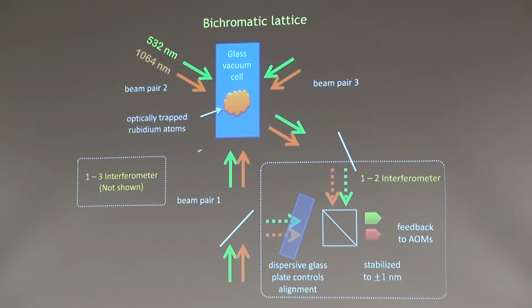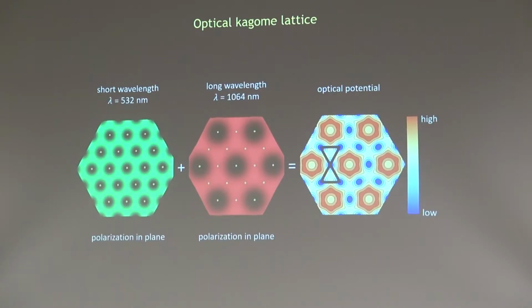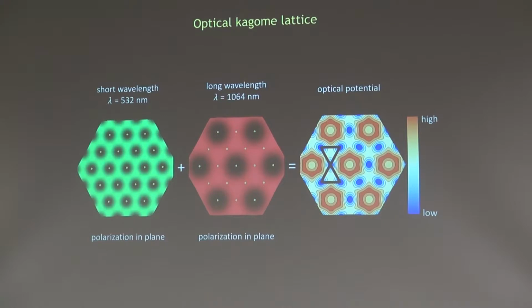And as I'll show you in a second, we're interested in forming an optical lattice or an interference pattern from the intersection of all these green beams. And on top of that, another optical lattice from the intersection of these infrared beams. But we're very interested in the relative position of these 2 optical lattices. And in order to stabilize that relative position against drift in mirrors and air currents and such on the table, we use some active stabilization at an interferometer, which now is tuned pretty well to where the relative position of the 2 lattices is stable to within about a nanometer. So that means we can create this kind of configuration within the vacuum cell.